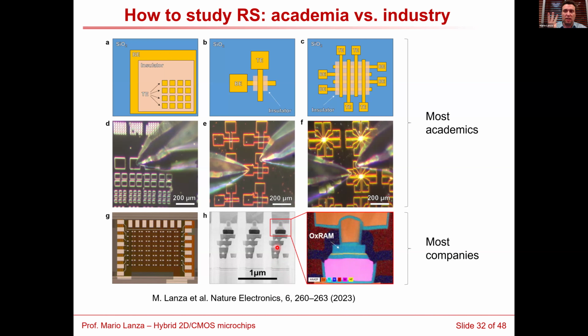Then the transistor provides 3 advantages. The first one is the transistor is the current limitation element, and the maximum current that it gives is defined by the gate voltage. There is no way of having a current peak because it's defined by the channel conductance. The second is that if we switch off the voltage in the gate, you can basically mitigate all the current across the memristor. So basically, you are mitigating sneak path currents from one device to another in the crossbar array structure. And the third advantage is that in the microchips, the bottom electrode, this thing here, first is very small, and second is very stable. So this is a big advantage to fabricate very small resistive switching devices.